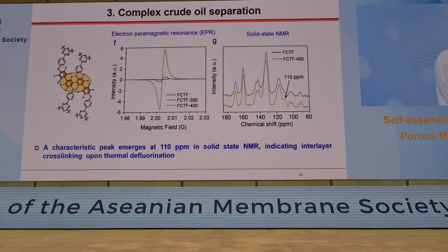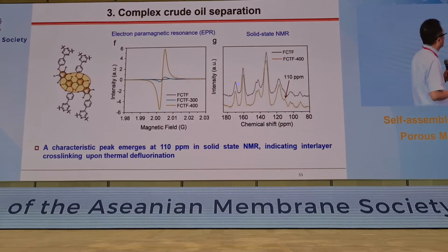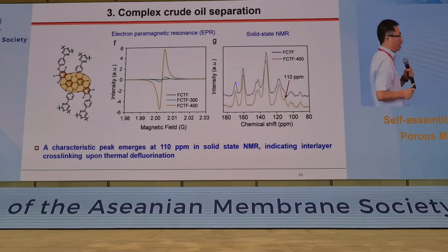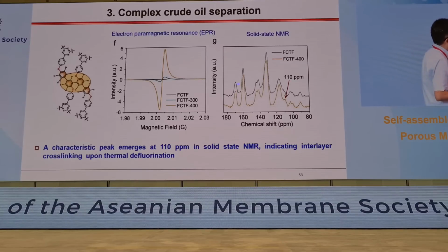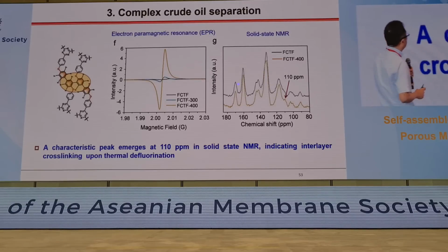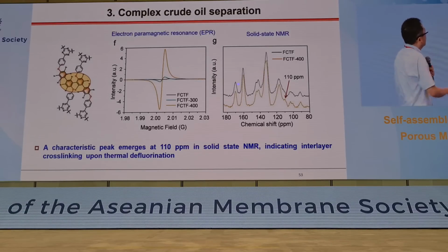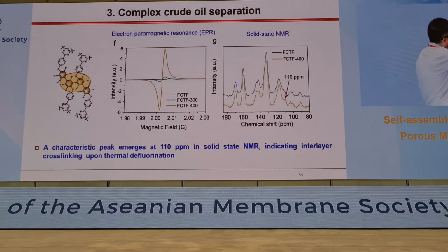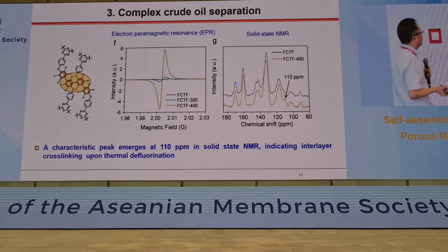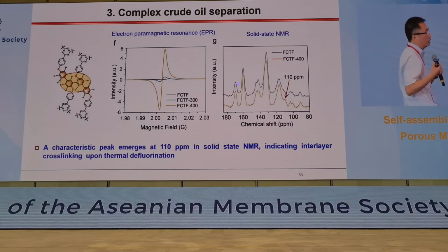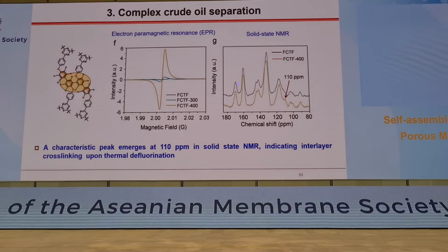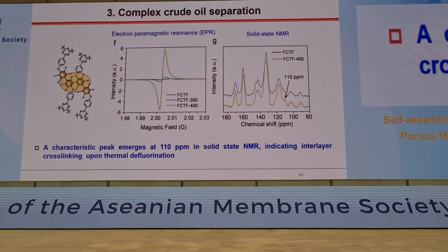First of all, we characterized the cross-link effect by electron paramagnetic resonance and also solid-state nuclear magnetic resonance spectroscopy. Through this EPR result, we can see a strongly enhanced peak. This one is attributed to stronger electron coupling, delocalization after cross-link.